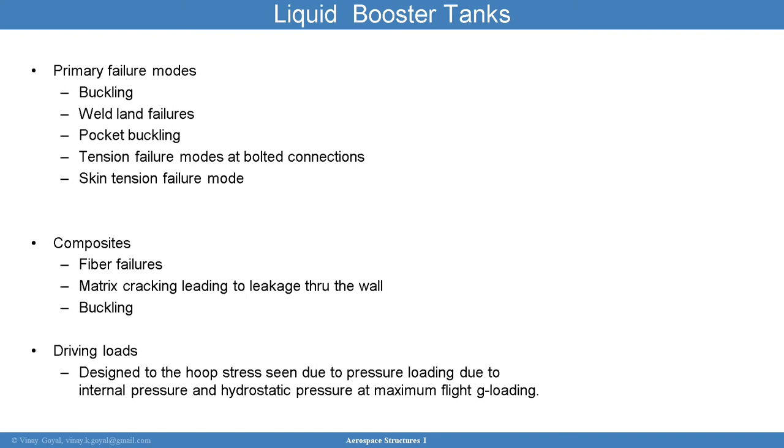Skin tension failure mode. And if you're using a composite tank, fiber failures and buckling can be a concern. And then matrix cracking leading to leakage through the wall should be considered, because if you use a composite tank with fluid inside, any amount of matrix cracking could then allow leakage to happen through the wall. The driving load in this design, they're really designed to the hoop stress seen during pressure loading due to internal pressure and hydrostatic pressure at maximum flight G loading.